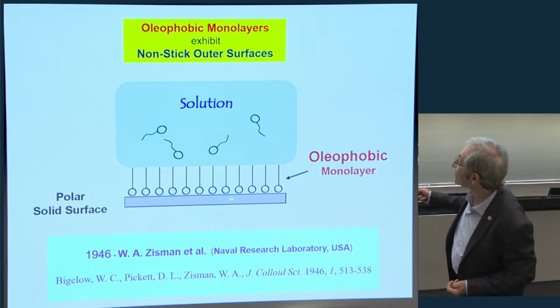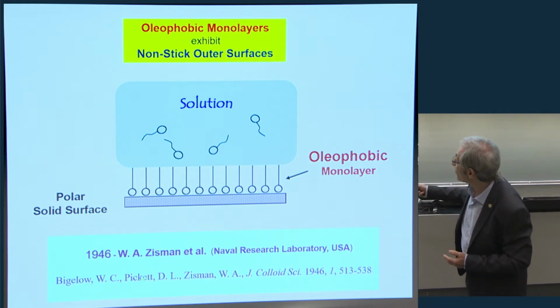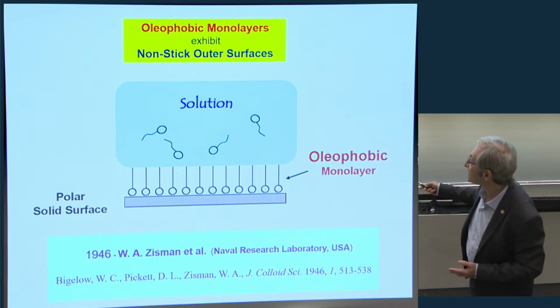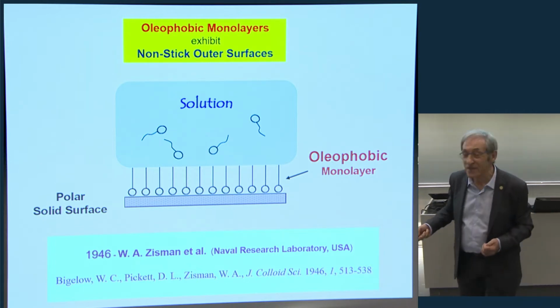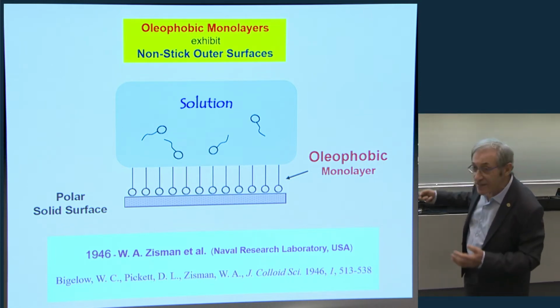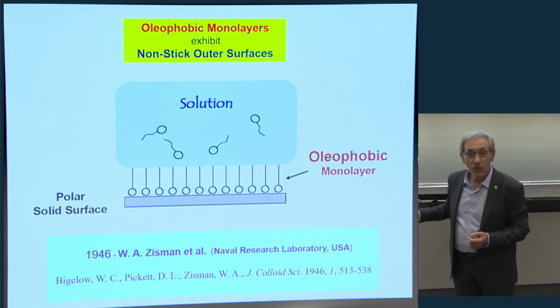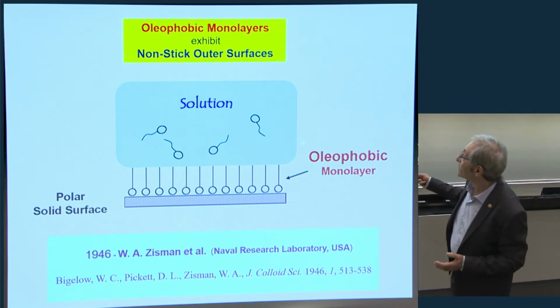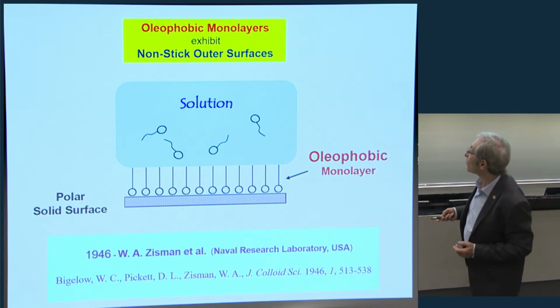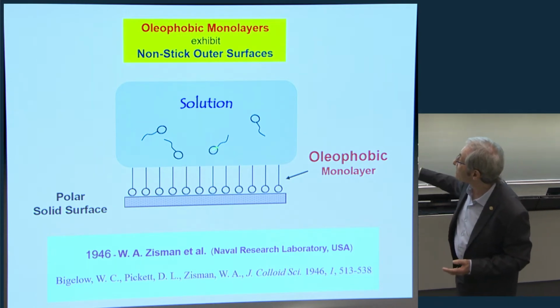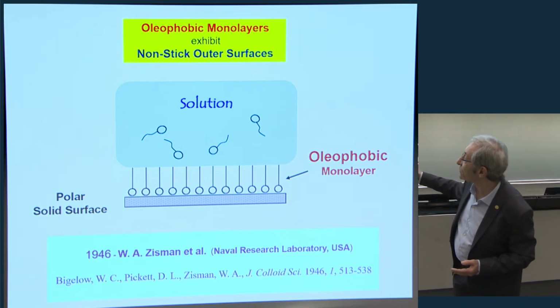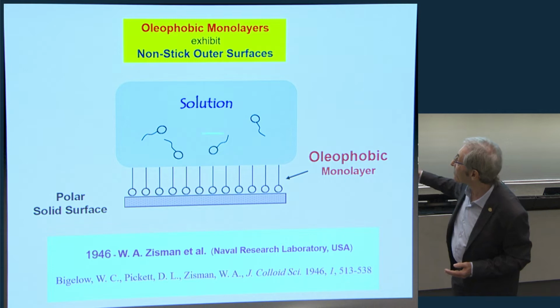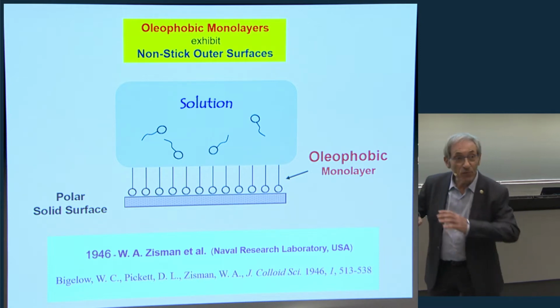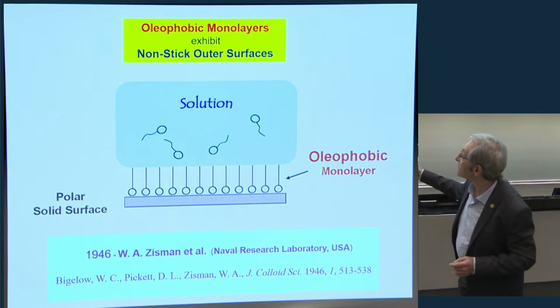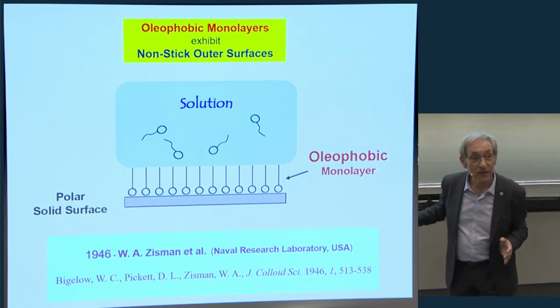So these are monolayers that are formed by, in the case of the group of William Zisman, they worked at NRL, Naval Research Laboratory in Washington, D.C. They investigated monolayers of long-chain fatty acids that form on metals, and they coined this term oleophobic monolayers. So again, you see what is the key feature here. You have these molecules floating in solution. This is the active ingredient. The solution is an organic solution. And once the monolayer forms, you get a well-defined droplet. It means the liquid doesn't stick, and these molecules do not stick, so you end up with a well-defined monolayer.